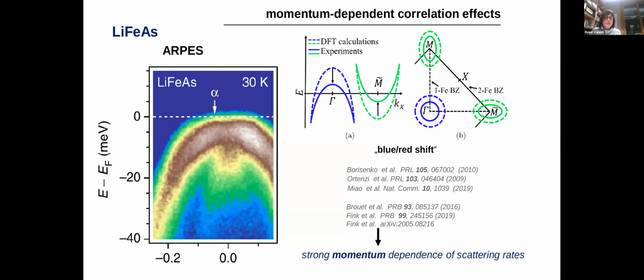Yeah, this is a very good point, because that's why we're having all this discussion with Antoine and with Gabi. I agree with you that it's not a simple problem. And in fact, you are talking about iron-selenium-tellurium, iron-selenium-sulfur, all these systems. In fact, iron-selenium is in some sense more complex, in my view, than lithium-iron-arsenic. It's more complex because we have there more features that we still don't completely understand, like, as you say, the disappearance of some spectral weight depending on the temperature. That's why we chose this material, which I classify as less strongly correlated. I mean, it's correlated, but less strongly correlated. And maybe we don't have to deal with these extra features.